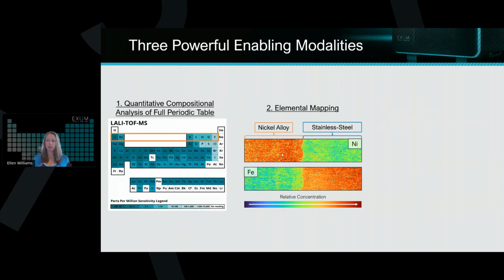As I alluded to, because this is a laser-based technique, we can also see how those elements vary spatially. We can create elemental maps on a millimeter scale with micron level resolution. The resolution of a map is defined by the laser spot size, and the user can adjust that from 5 to 150 microns, allowing us quite versatile mapping capabilities, and we're going to show a few examples of that going forward, of being able to do broad scale coarse maps combined with high